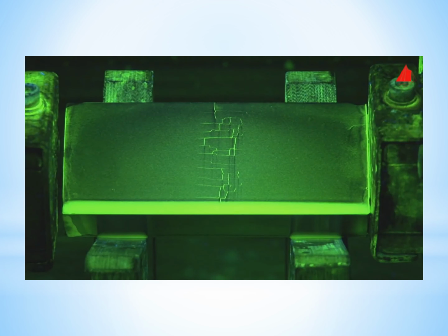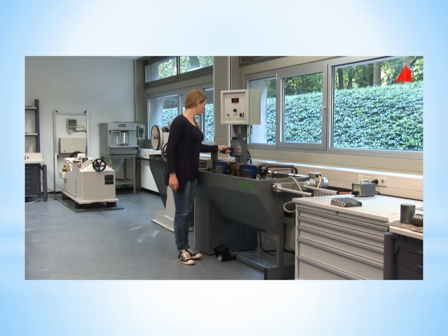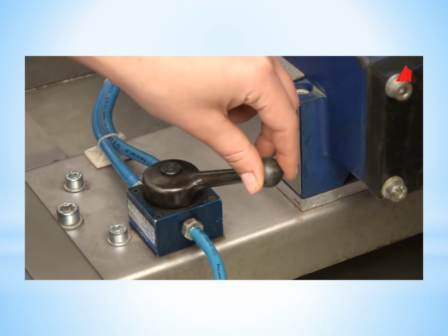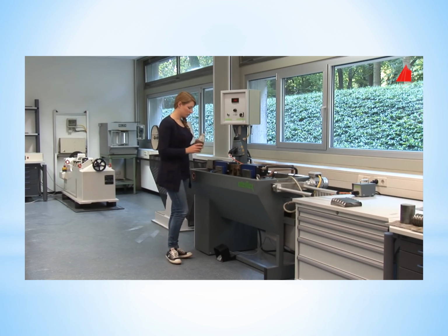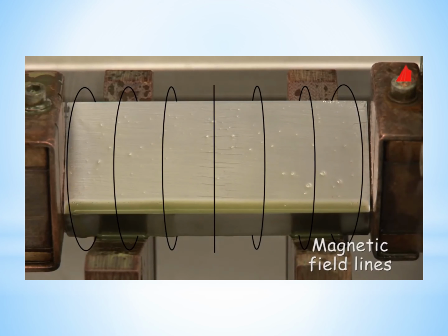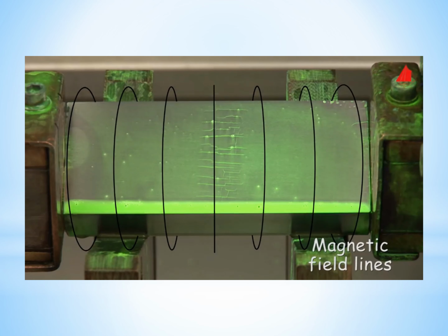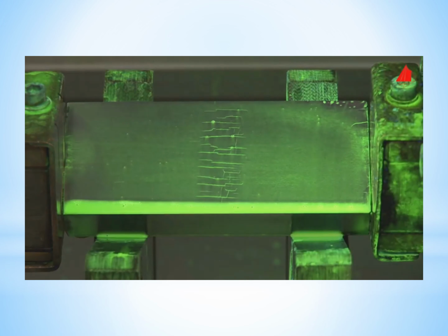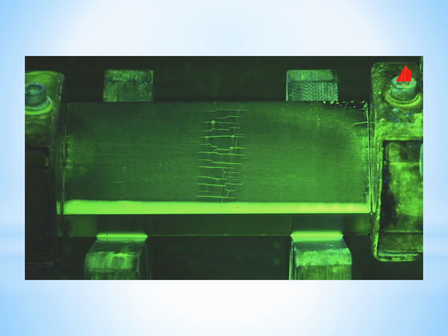To make sure to detect all near-surface cracks, one has to magnetize the sample once more and best perpendicularly to the first time. To do this, the material tester switches the machine over to the current flow method. A high electric current flows through the sample, generating a circular magnetic field. Now the cracks in horizontal direction can be seen very well. The tested sample is a hardened sliding guide. The cracks have been formed during the hardening process and the subsequent grinding operation.